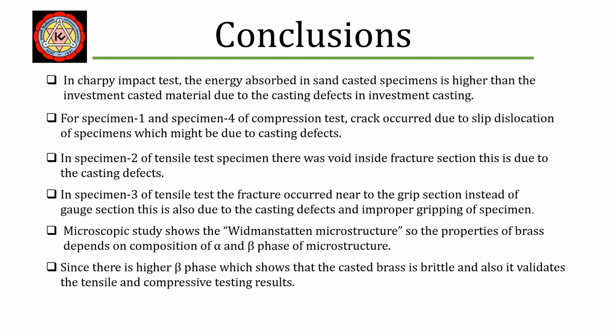In specimen 2 of the tensile test, there was a void inside the fracture section. This is due to the casting defect. In specimen 3 of the tensile test, the fracture occurred near the grip section instead of the gauge section. This is also due to the casting defect and improper gripping of the specimen.